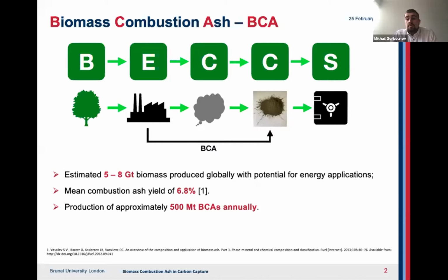So the feedstock is becoming more and more desirable, and currently the global biomass production is between 5 to 8 billion tons per annum. However, combustion of this feedstock leads to ash formation, with a mean ash yield at about 6.8%, which would equal to around 500 million tons of BCAs every year. However, BCAs have different properties to coal ash: elevated alkali earth, metals, oxides, hydroxides, carbonates, and more mobile hazardous compounds.